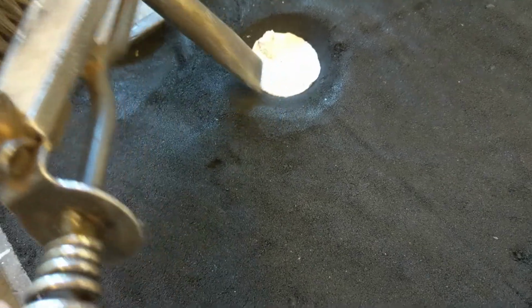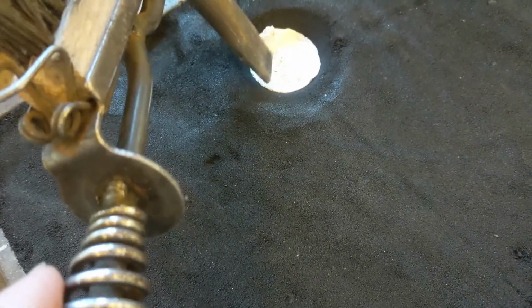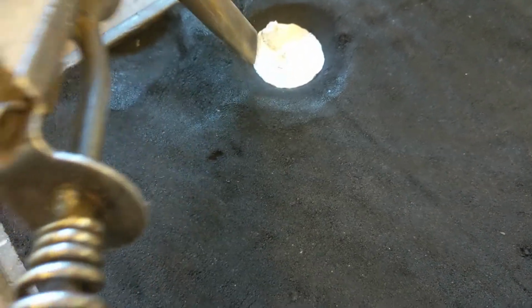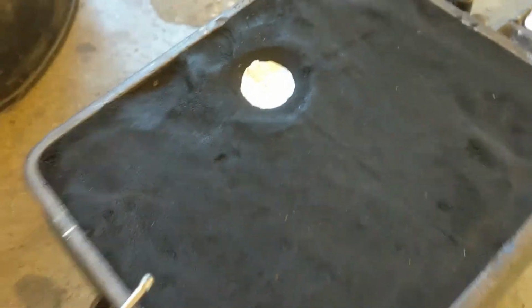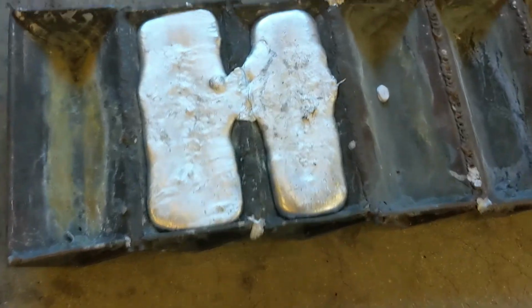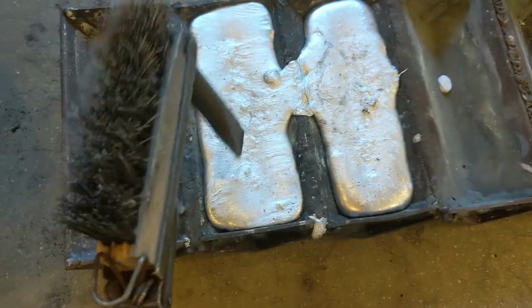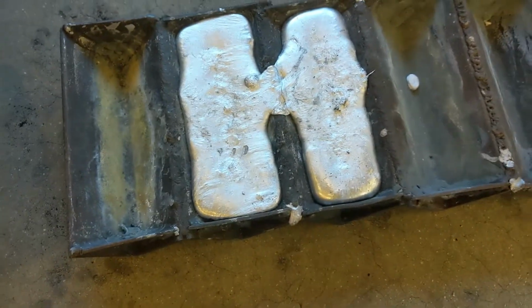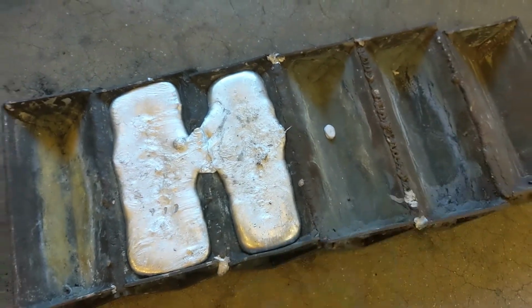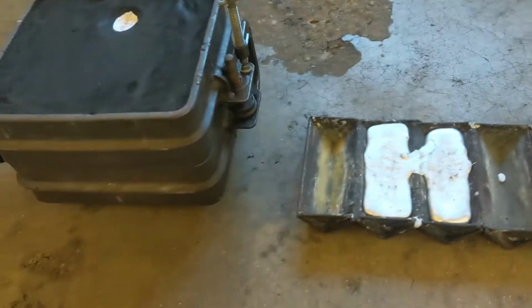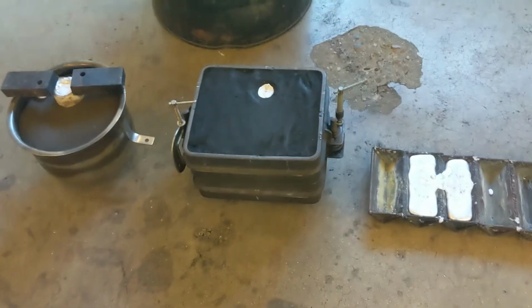Move on to the green sand casting. The first thing you'll notice is that what was once a flat surface is now concave. It's a little bit mushy in the middle, but it's somewhat solidified. That's that aluminum shrinking as it cools. And then lastly is the ingot, and this ingot has now solidified completely. It's chilled by the steel. So there's 3 different examples of the insulating properties of these different materials.